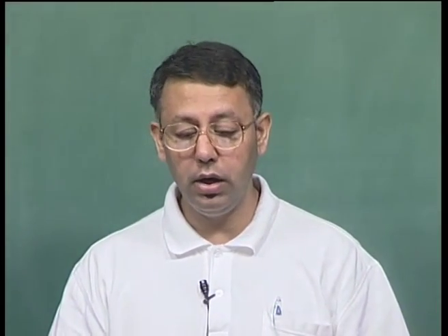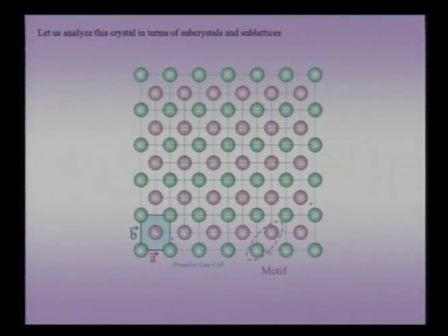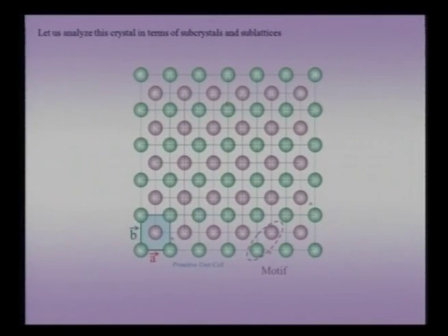Now it could so happen, and typically it does happen that way, that many of these systems show a disordered alloy at high temperature, wherein you would have a simple kind of structure. In other words, the central lattice position would be decorated by something which is exactly identical to the one at the corner. But at low temperatures, if the structure gets ordered, which is what you can see here, this is an ordered structure wherein the brown circles occupy a particular sublattice preferentially compared to the other one.